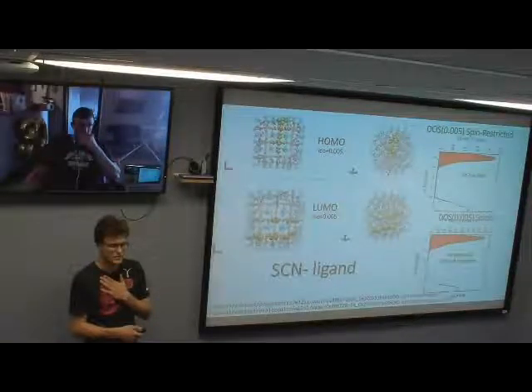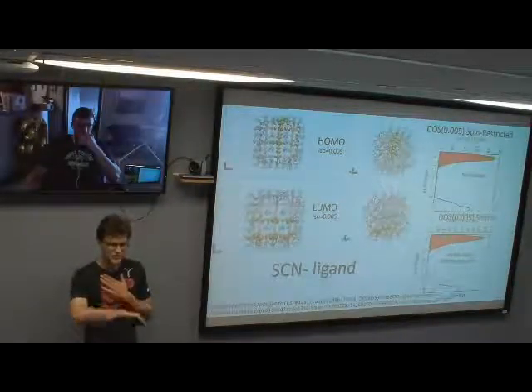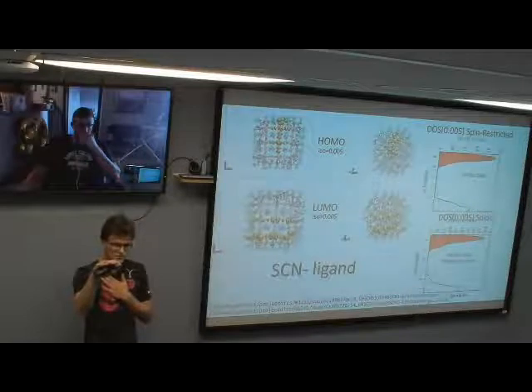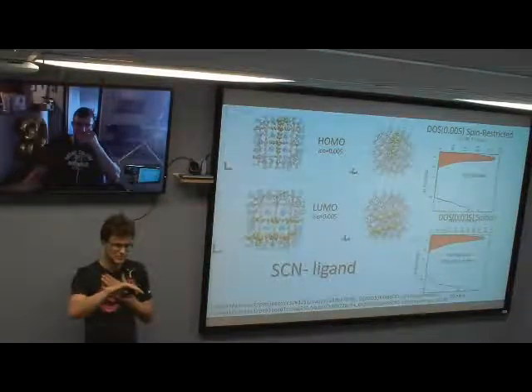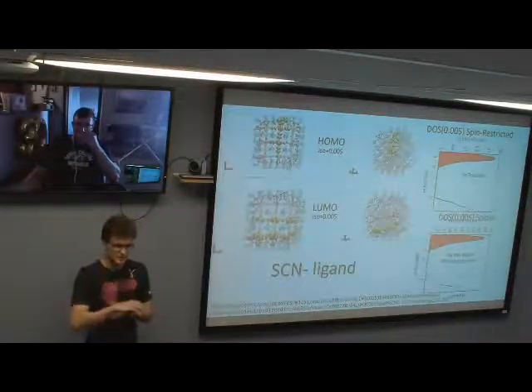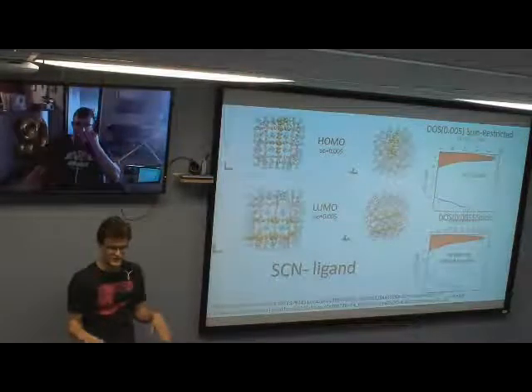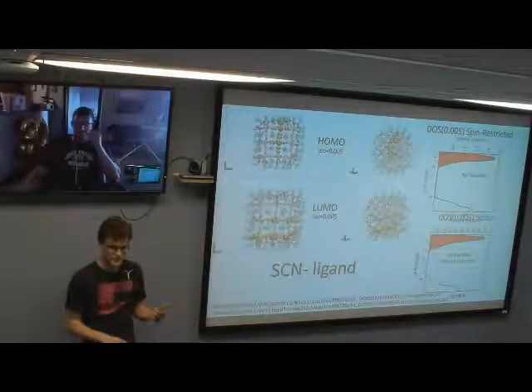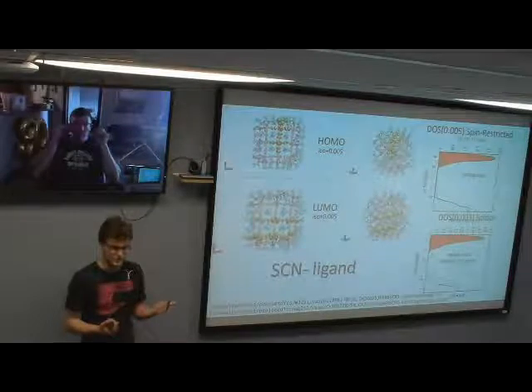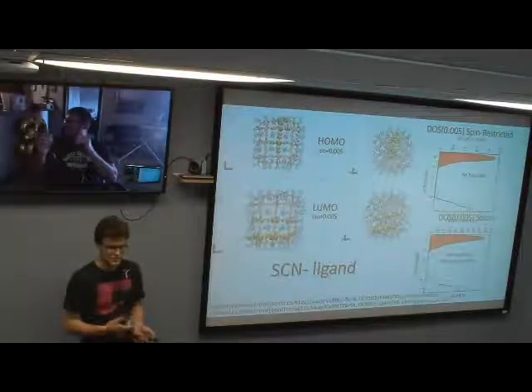I think in that paper they noted there was a saturation point, so they'd see a certain amount of ligands attach, and then after the initial 20 minutes there would be no more passivation. So it seemed to be limited by either surface states or some sort of equilibrium within the solution concentrations.